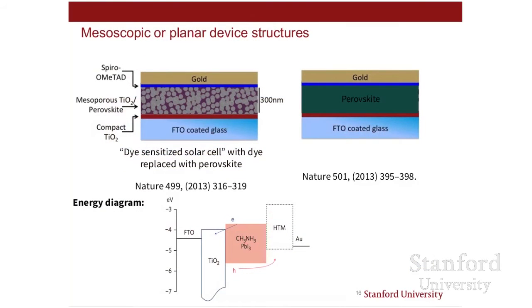On this slide, you can see the cross-section of a typical perovskite solar cell. On the left was the original composition that a few labs like Namgu Park, Tom Miyasaka, Henry Snaith, and Michael Gratzel discovered. And it evolved from the dye-sensitized solar cell. It has a film of titanium oxide nanoparticles filled in with the perovskite and then sandwiched between a gold electrode and a transparent fluorine-doped tin oxide electrode. But pretty quickly, Henry Snaith realized that you don't actually need the titanium oxide nanoparticles, and you can use the planar structure on the right, where it's just an uninterrupted film of perovskite.